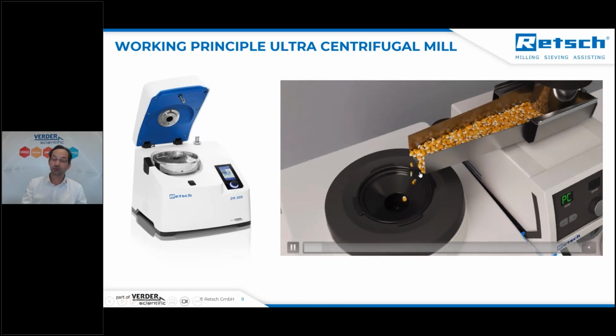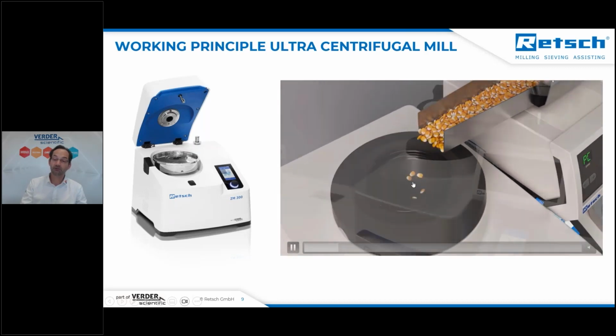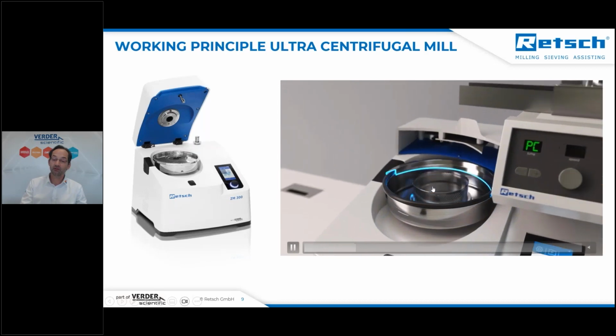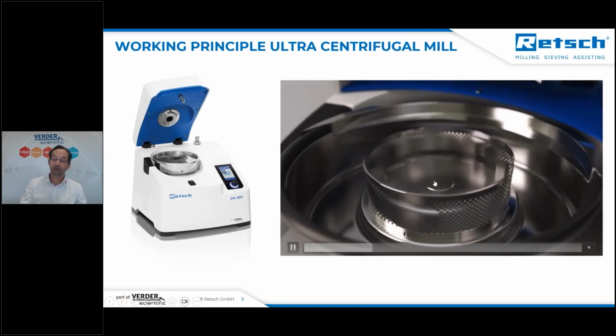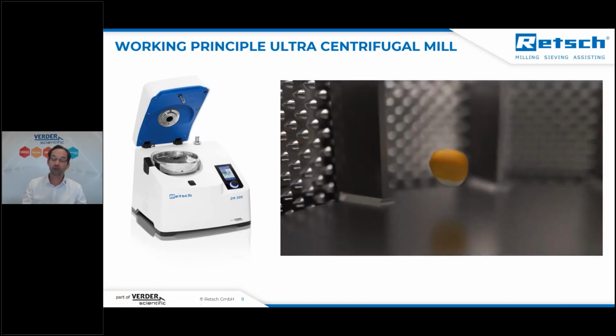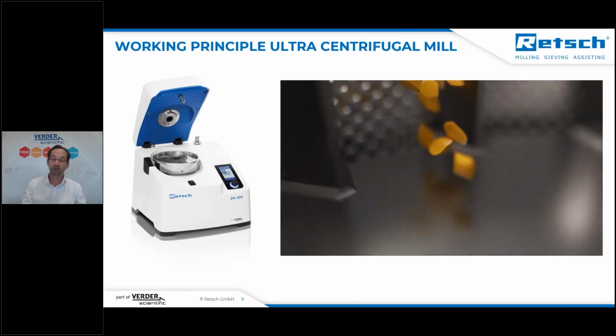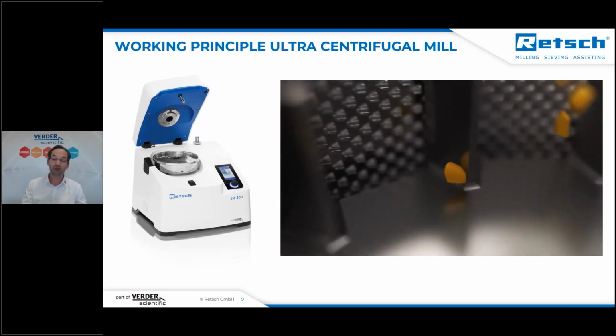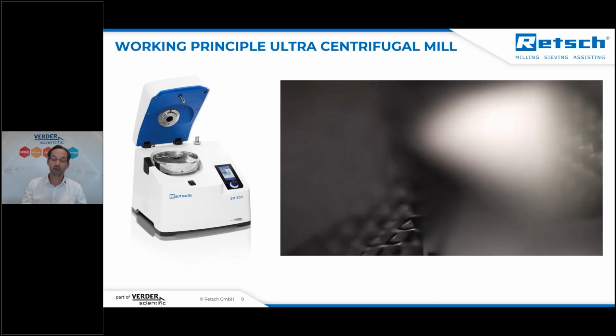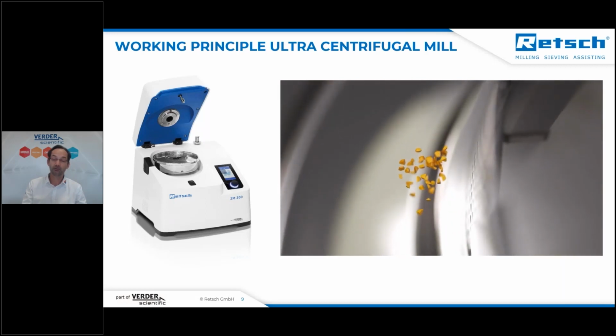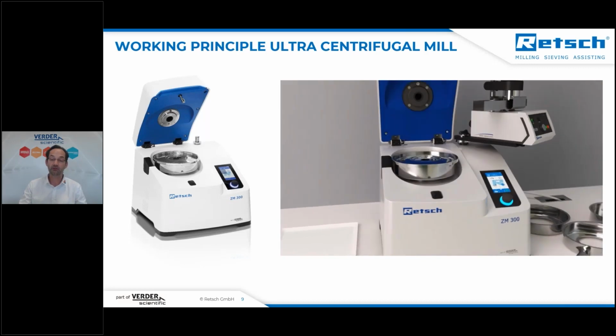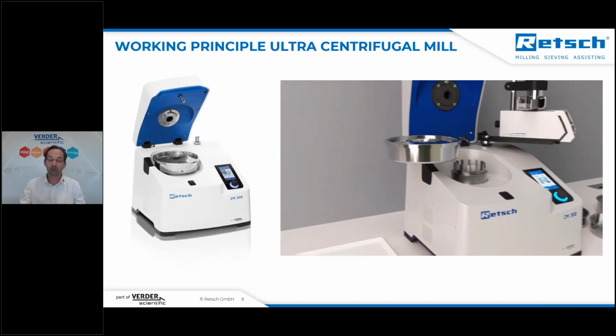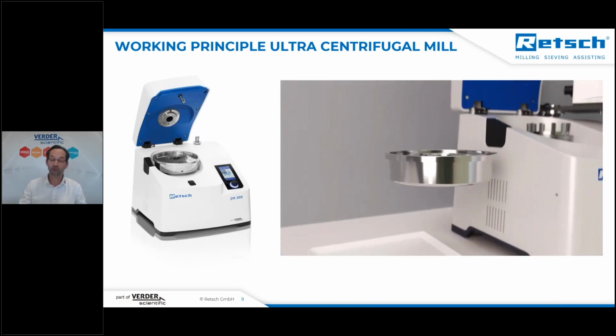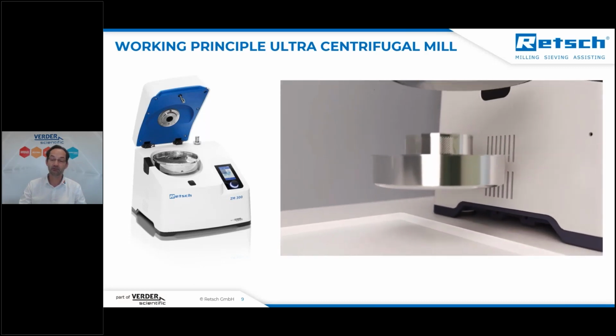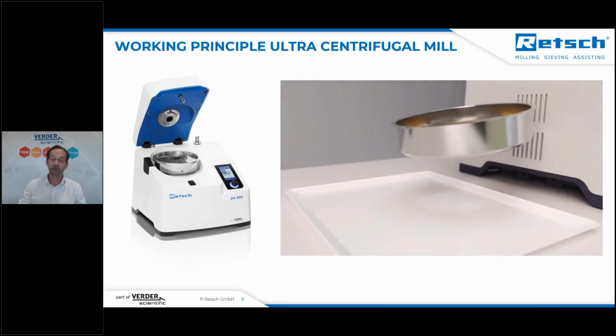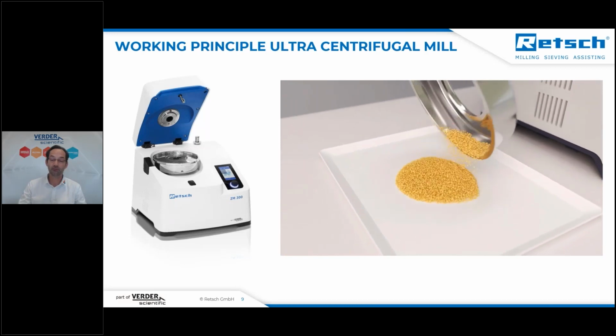So the material drops in either manually or with a feeder like shown here into this cassette. It enters the grinding chamber where the rotor is rotating at very high speed, and this causes the sample to impact against the rotor teeth, and subsequently it is ground by shearing along the sieve which surrounds the rotor. And depending on the opening of this sieve, you can create very fine powders or eventually even coarser sizes. And then the sample can be taken by just taking out the cassette, and you've got your fine powder to be used for the next step.